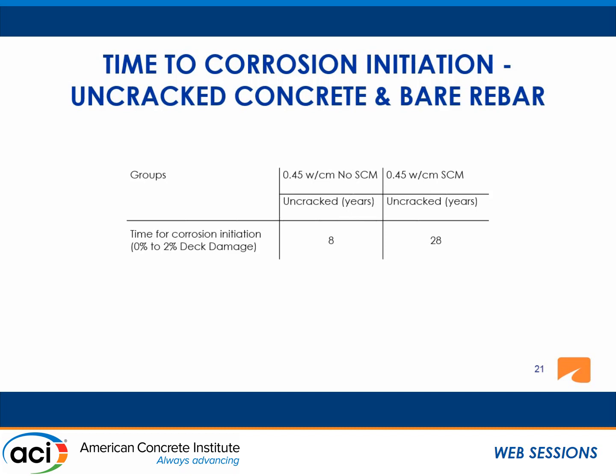This is a simulated model where we took all the chloride diffusion parameters for these two groups and applied it only for those factors we found on the uncracked surface, just the solid concrete. If the concrete never cracked, the plain concrete with no SCM would have corrosion initiation at about 8 years. And for the supplementary cementitious materials, for a similar design, the time to corrosion initiation seemed to be more than three times as much, at about 28 years.